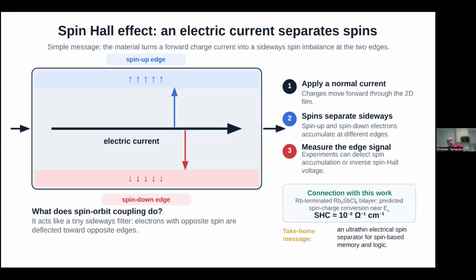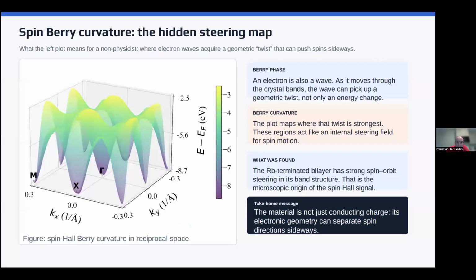The spin Hall effect is another story. When we speak about the spin Hall effect, we have spin orbit coupling, to recall the previous slide. We split the electronic current that passes into a spin up edge and a spin down edge. And what we have found here was quite a high spin Hall conductivity, in the order of other compounds seen in the literature, for the bilayer of the rubidium terminated. In more detail, our result comes from the Berry phase. If we think that we have an electron, the electron is also a wave and it moves in the crystal.